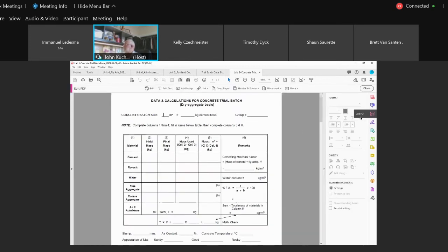So if we looked at the example, and I'll switch that right away here. The concrete batch size here, we're going to look at 0.1 cubic meters. So really, your coarse aggregate mass for 1 cubic meter multiplied by 0.1 is going to give you your initial mass there. Fine aggregate, whatever you worked out, dry basis per cubic meter times 0.1 goes in there. Same with the water. Same with the fly ash. Same with the cement. Pretty straightforward.